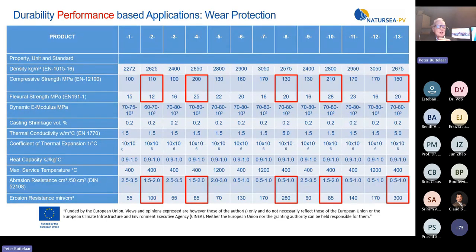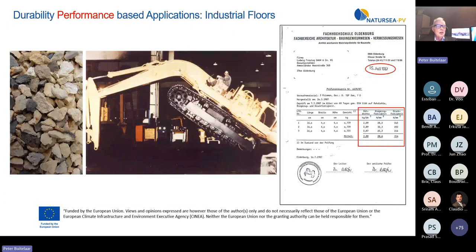We also see that UHPC designed for optimum protection against wear doesn't show any relationship between compressive strength and abrasion and erosion resistance. The type, quality and dimensions of the special aggregates embedded in the strong grip of the UHPC binder are responsible for the wear resistance and impact resistance. For industrial floors, pavements, concrete repair and bridges, other properties and durability are required. The combination of extremely hard aggregates and steel fibers, durably fixated in dense UHPC, results in extremely high wear and impact resistance.